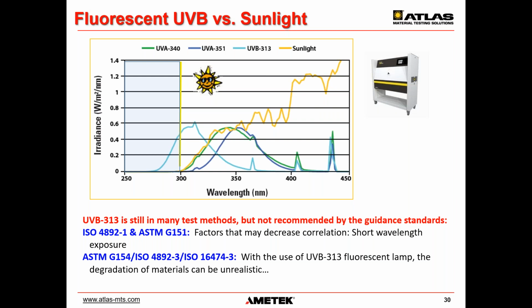But this is past. However, one must be careful about the possibility of unnatural degradation. In some cases, the photochemistry can be so altered that the product passes the test but fails in normal sunlight. This happened with the first automotive base coat clear coat paint system failures, a very expensive learning experience.